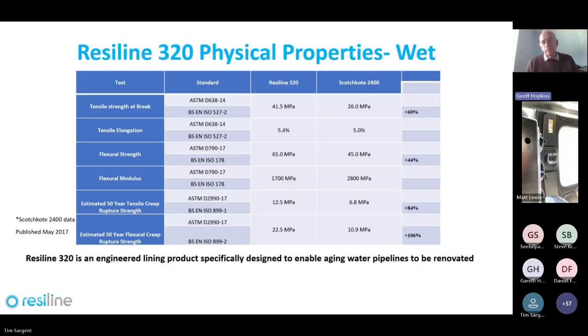And this is short-term figures. You would get these results in about a month, let alone 30, 40, 50 years. So that's the dry properties. What that translates down to is the bottom two rows on that chart, which show the projected 50-year tensile creep rupture strength, which is needed for fully structural linings, and the projected 50-year flexural creep rupture strength, which is what you need for covering holes in partially deteriorated pipes. And basically, in both of those rows, you can see that the Resiline values are more or less about double what they are on the second generation 3M material.